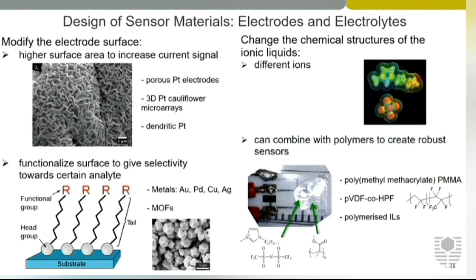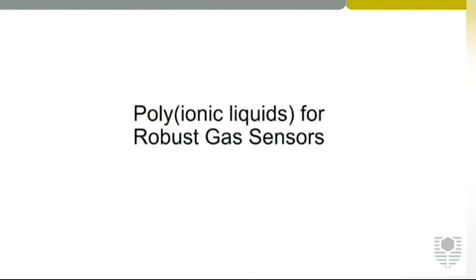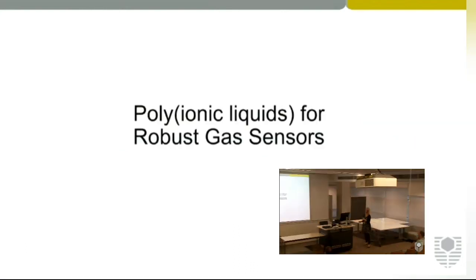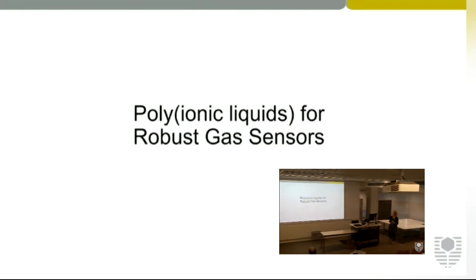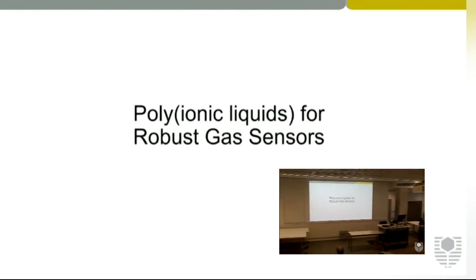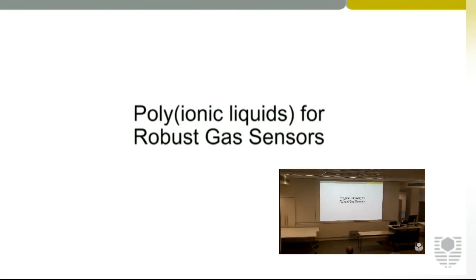PMMA mixes very nicely with ionic liquids, and that's what this is here. So you end up with a kind of gelled material on the surface. We've also used this copolymer, which is quite hydrophobic as well. And then what's really interesting, and we've been getting the best results with, is polymerized ionic liquids. So I'm just going to spend a few minutes talking to you about why I think polyionic liquids are really exciting for robust gas sensors.